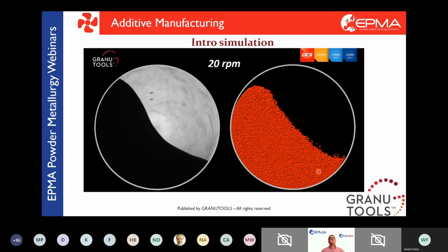And what is good is that we can still follow the process conditions, because we can take several pictures at 20 RPM, 60 RPM, and then do the same simulation inside the software, and set up parameters for the model that will match, let's say, match the interface the best at the speed we want to work at.